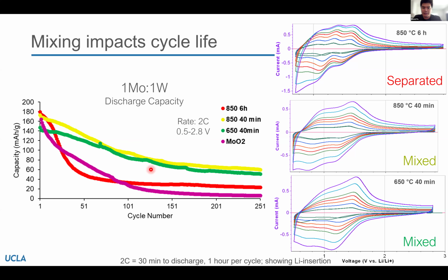And just a couple things to notice here is that our separated solid solution crashes its capacity despite them all starting at around the same. The intermediate one loses a decent amount, and then the mixed solid solution, while starting at a lower overall capacity, has the highest capacity retention. So over 250 cycles, it's able to maintain more of its capacity compared to the other solid solutions.